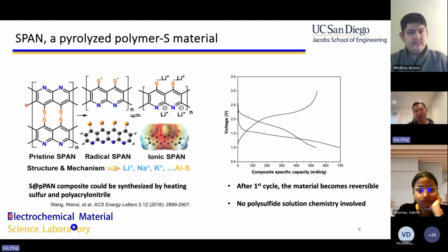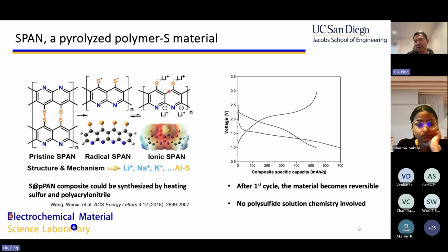You heat up a polymer called polyacrylonitrile with elemental sulfur in a tube furnace under inert atmosphere at about 350 to 400 degrees C. You get this black powder. In case you're not familiar with polyacrylonitrile, that's the precursor people use to make carbon fibers. At Georgia Tech, Professor Satish Kumar is a world-renowned expert in PAN material. If you make this material, you get this discharge curve, and the capacity does not look too exciting. It's 550 instead of over 1,000. But what's amazing is that the material, unlike elemental sulfur, cycles forever.